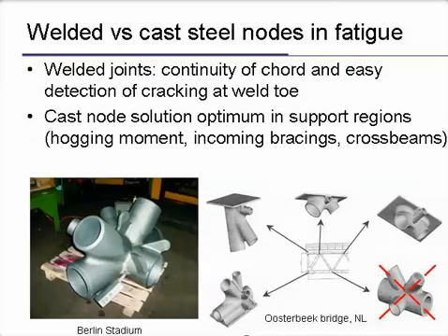Now, if I look into fatigue or also in general, we'll see that there are advantages using welded and advantages using cast steel. Welded joints, you have a continuity of the chord, and it's easier to detect the cracks because they are at the weld toe. But the cast node solution is optimum in support region. So in fact, in the end, you find this kind of thing. Here is a bridge that was done in the Netherlands. You find that the optimum is to use both.